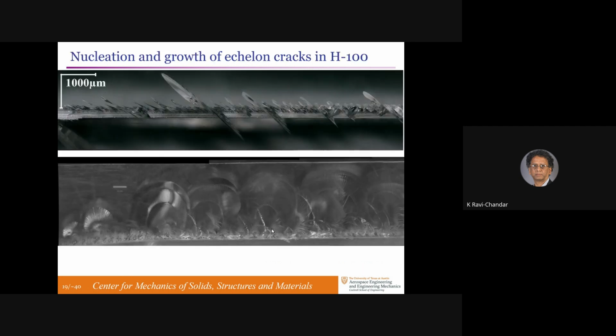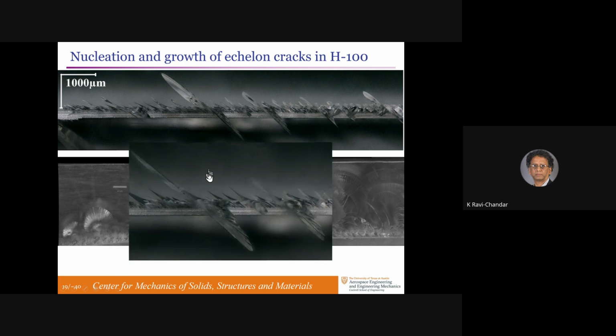And we found in our experiments the same thing in a different material. This is now a brittle polyester. Those are the daughter cracks. Parent crack is over here. They're tilted at an angle of 45 degrees for the mode 3 loading. And you can see many families of daughter cracks. So that's the third family, that's the second family, there's the first family that's even smaller. So there's a coarsening effect of these cracks as they grow.